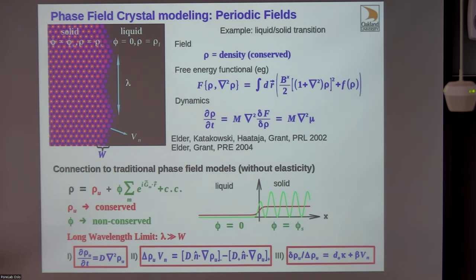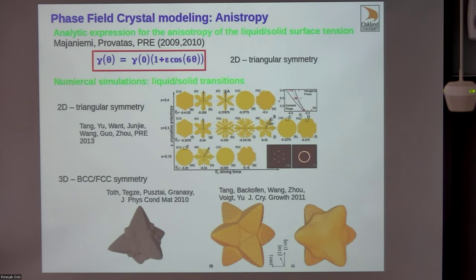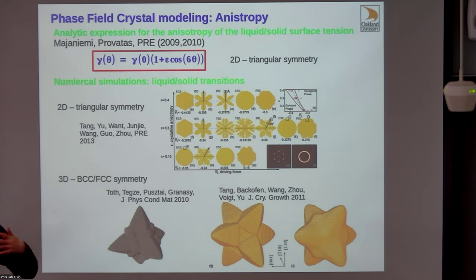If that were all you got, it wouldn't be worth doing. Of course, you get extra physics—you automatically get anisotropy because now we have a crystal structure. The energy of an interface depends on orientation. There are analytic calculations for the 2D triangular case, and you can use them to study shape transitions—how the shape of growing crystals depends on flux, temperature, and various quantities.